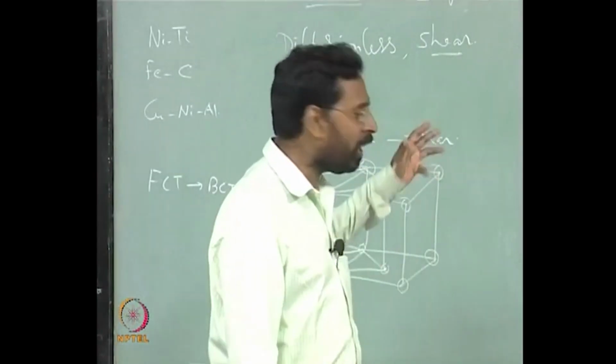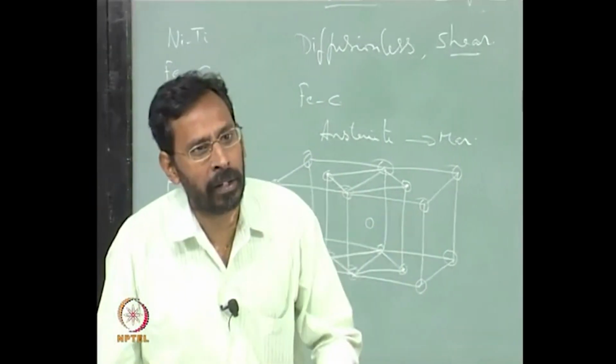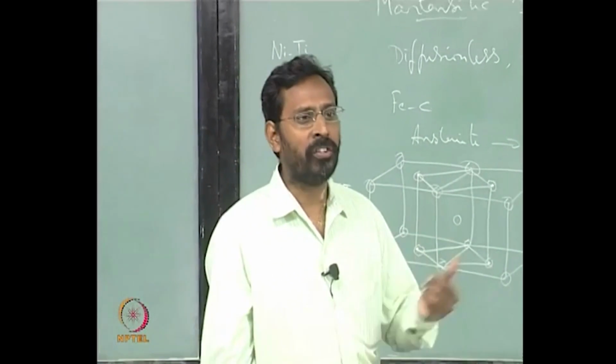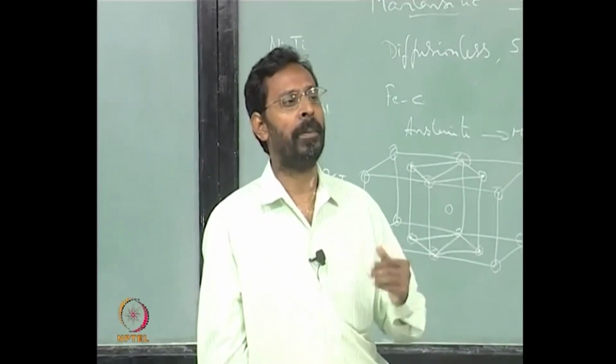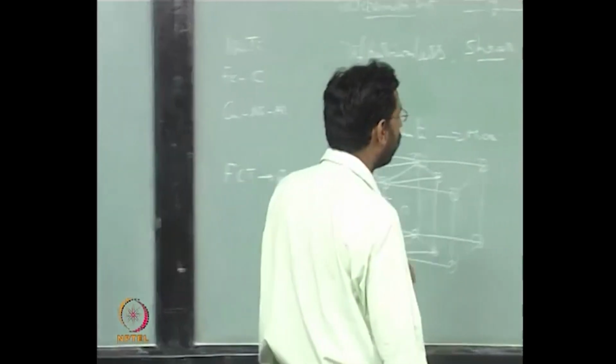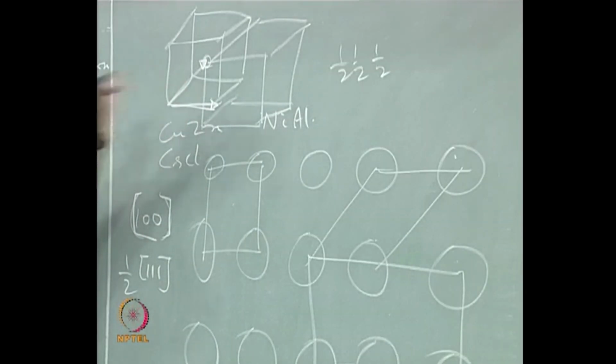So you would see that the moment it becomes ordered, the deformation occurs on different planes. It now starts searching for different directions where slip can easily occur, and obviously you will never find a shorter Burgers vector once you are a superlattice. As a result, you will see the deformation becomes more difficult, and you will see many other things. Okay, come back to here.